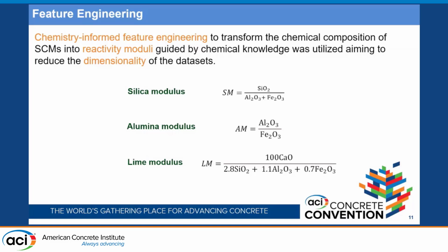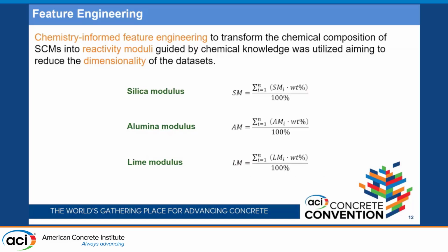So one option that we are exploring is using chemistry-informed feature engineering, where we can convert the chemical oxides into some reactivity modulus, for example, silica modulus, alumina modulus, and the lime modulus. And then we can take an average over the binder system that we have, and instead of using 24 different chemical oxide binder contents, we could use 3 of them for the whole binder system. Here we can actually reduce the dimensionality of the data set.